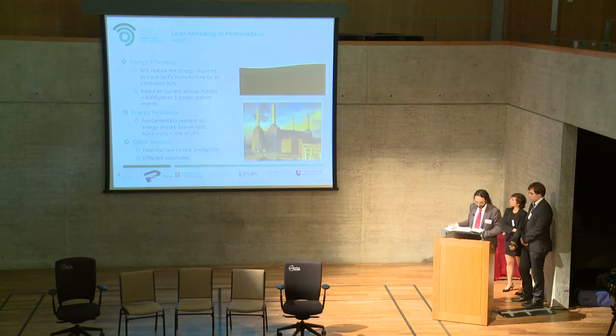So the impact that we are going to reach, hopefully. We need to reduce the energy required for the manufacturing of these PV cells by 30%. 30% means that, based on the previous statistics of 1 gigajoule, we are hopefully going to reach 700 megajoule per square meter. And if we apply the same saving to the current global market, we are going to save something like 800 gigawatt hours, which corresponds to 1 month of a power station.